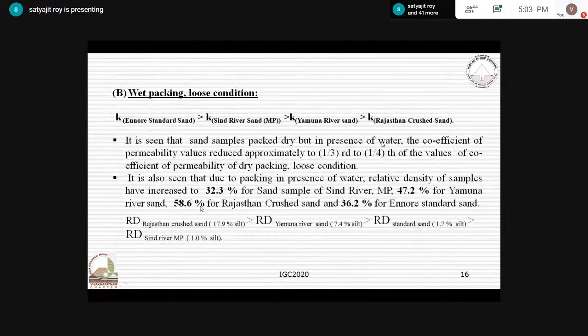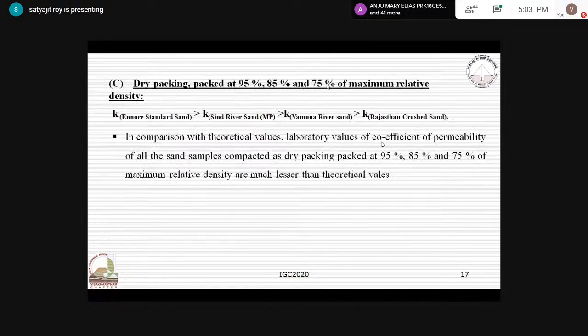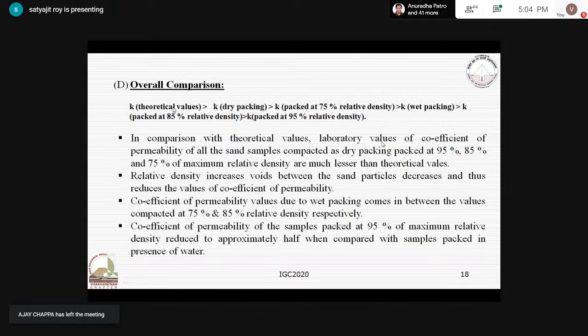Now the wet packing. I have packed the sample in the presence of water also, and interestingly, it has been seen that when I pack the sample in the presence of water, the relative density of sand has increased in the range of 32 to 58%. Now the dry packing at 95, 85, and 75% maximum relative density has followed the trend that Ennore sand is the highest and Rajasthan crushed sand is the lowest value.